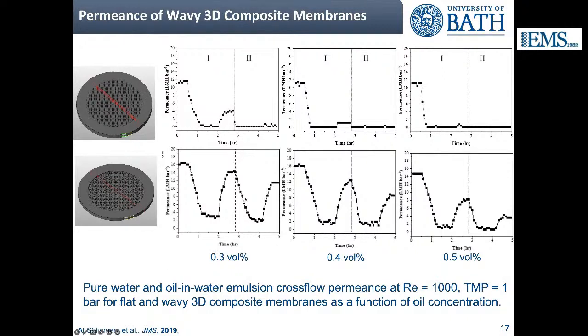What you see here are two rows of results for oil and water emulsion done in cross-flow using a flat membrane at the top and a wavy membrane at the bottom. So both have the same PS selective layer, but one is flat and the other one is wavy. Reynolds number is 1000 and transmembrane pressure is 1 bar for both membranes. So everything is the same, except one is flat and one is wavy. And we do two fouling cycles here.